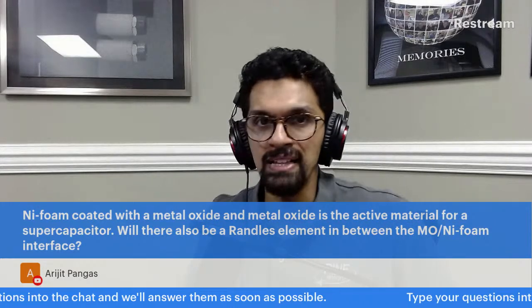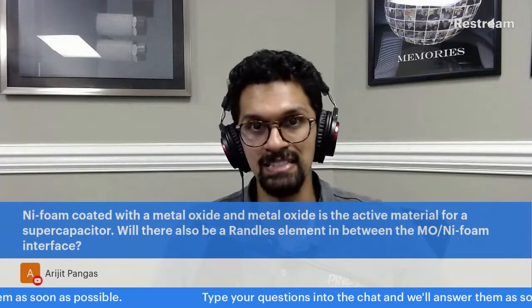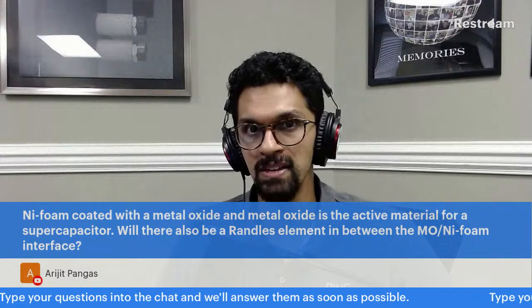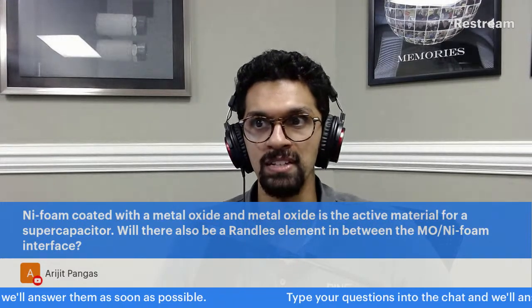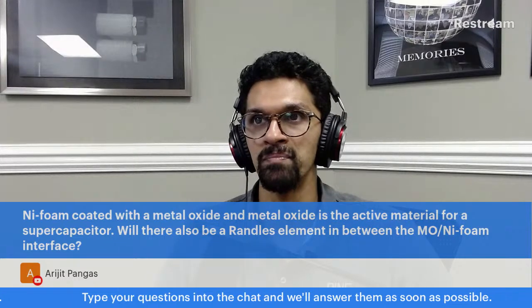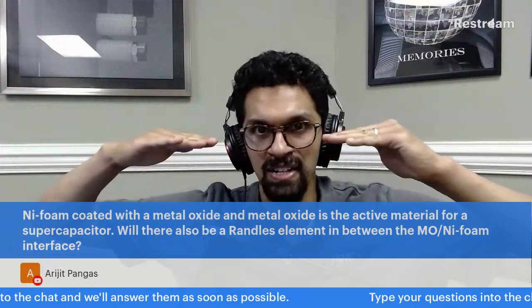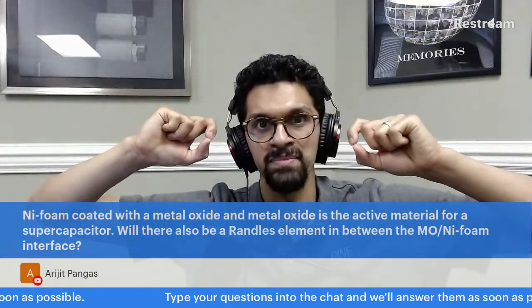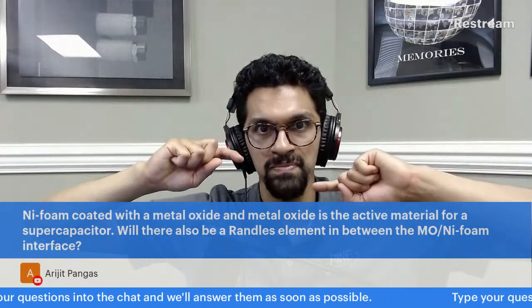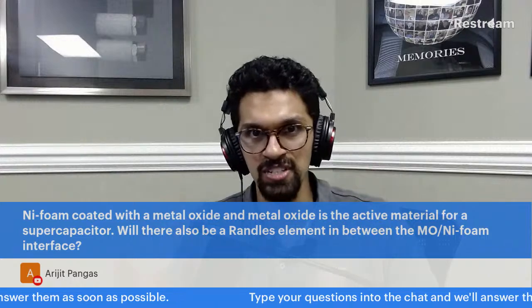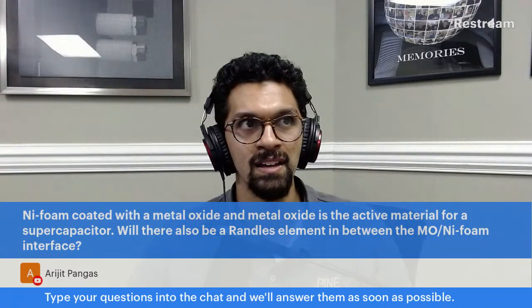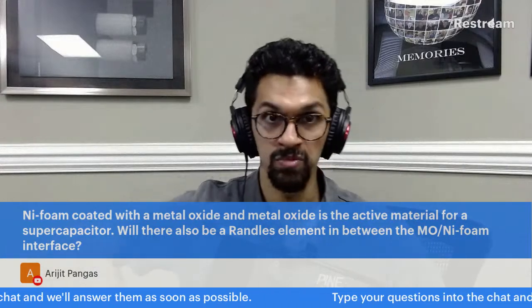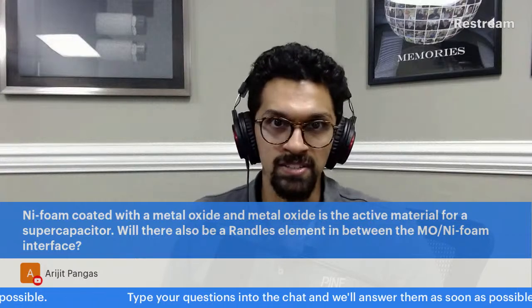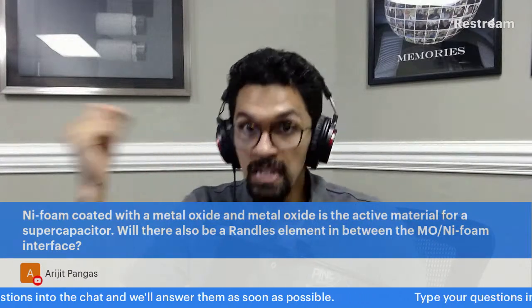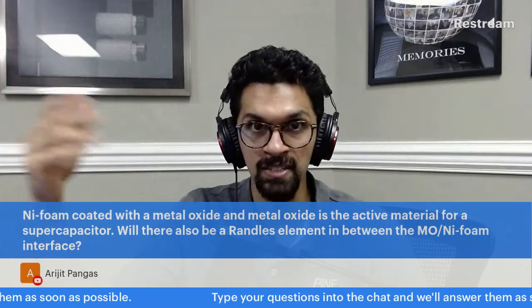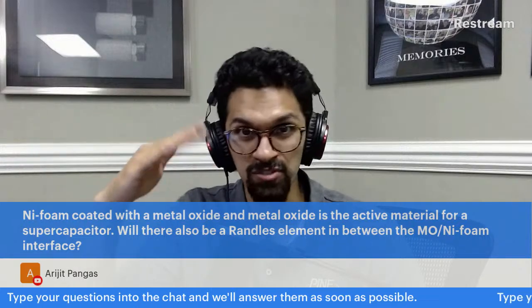So if the metal oxide is producing enough of an insulator between the nickel foam and the nickel oxide, then you can have capacitance. But it can also just be a resistor, because you could have a layer of nickel atoms and then a layer of nickel oxygen atoms, and all you're dealing with is electron transfer between them. So only if there's a sufficient thickness of this nickel oxide, and some kind of capacitor, charge separation, is there a Randles element. Otherwise it's just resistance, and there's just charge transfer between nickel of two different oxidation states. Metal nickel and then nickel oxide have two different oxidation states. You can have electron transfer between those two.